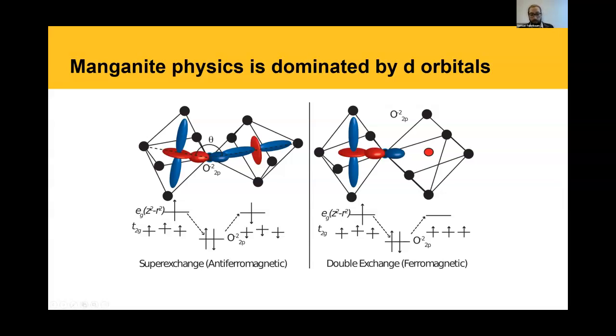So one thing to understand is that manganite physics is dominated by d orbital interactions. Every manganese atom in the system is generally in either a manganese 3 or a manganese 4 oxidation state. In these slides, I've shown you the d orbital manifold drawn here in the cubic configuration, where you have an Eg orbital and a T2G manifold. And because of Hund's rules, you end up getting 1 electron on each of these orbitals.